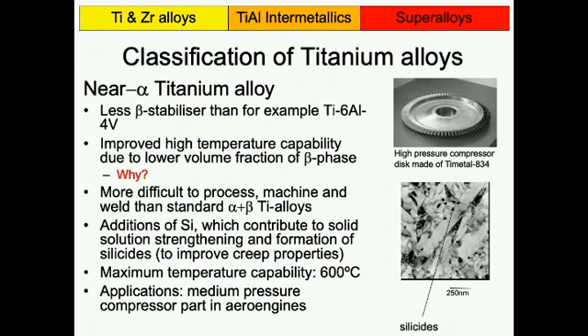Although I have to say that I don't think people have fully agreed on whether it's the silicides which really help a lot, or the silicon which is left in solution, which also seems to help in pinning the dislocations and maybe reducing diffusional climb of dislocations. I don't think researchers ever really got to the bottom of that. But overall, silicon has a very good positive effect at high temperatures. Maximum temperature capability of these alloys is around 600 degrees C. And so applications are the medium pressure compressor part of an aero engine.